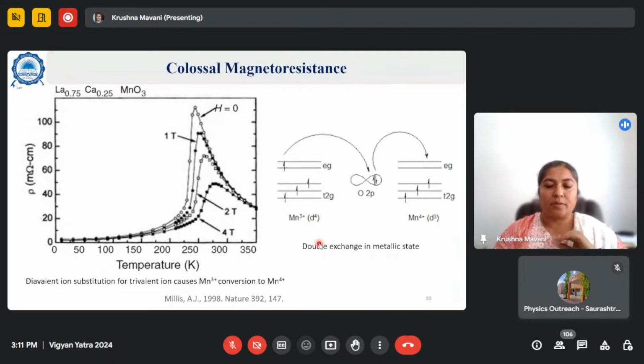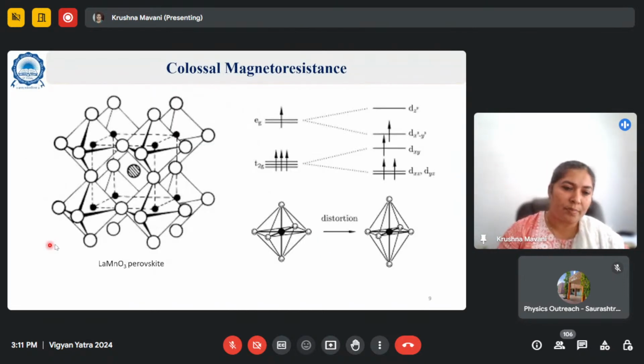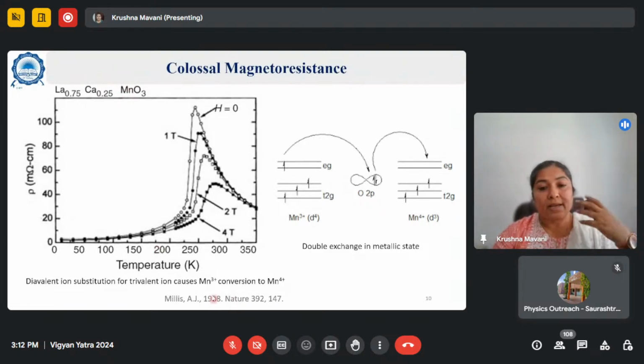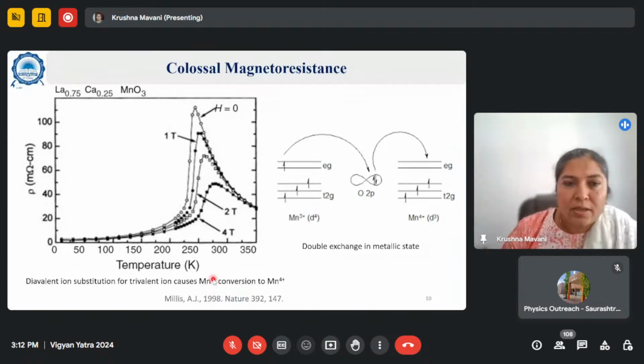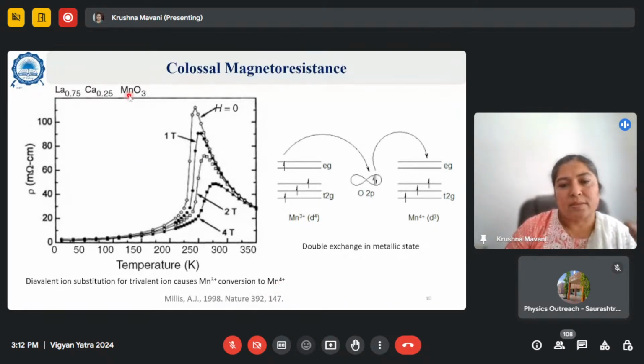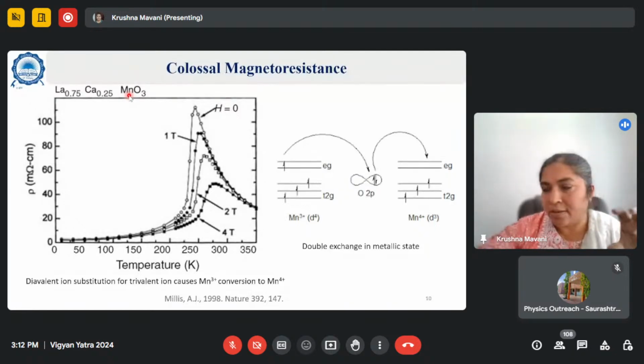What happens is, this was the pure LaMnO3 perovskite. When I dope calcium at the lanthanum side, you substitute maybe close to 25%. What do you see here? You have manganese converting into the 4+ state. You have manganese in the trivalent state initially. After divalent doping, it converts to the tetravalent state. So you can see 25% manganese ions in the tetravalent state here.